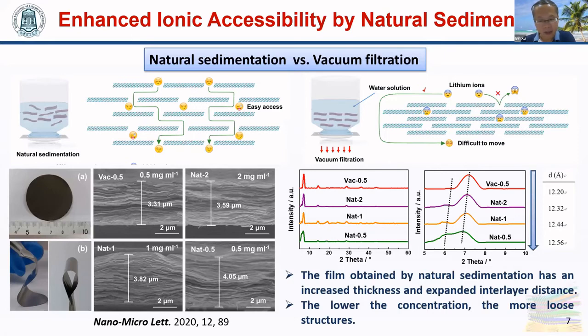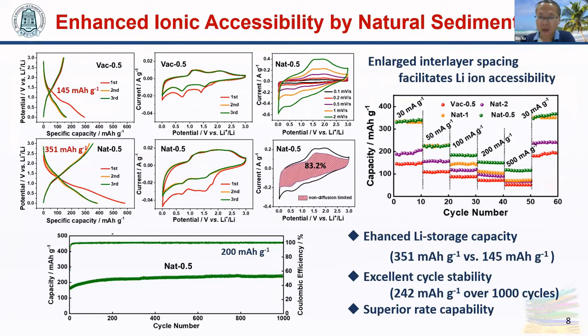The thickness and interlayer distance were influenced by the concentration of the MXene solution. The lower the concentration, the more loose structures will be obtained. The enlarged interlayer spacing facilitates lithium ion accessibility. Therefore, the MXene film exhibits enhanced lithium storage capacity. It can reach 350 mAh per gram, almost double that of conventionally prepared MXene films. It also shows excellent cycle stability and superior rate capability.